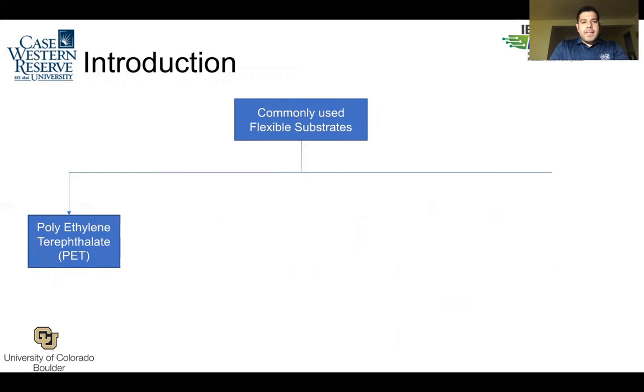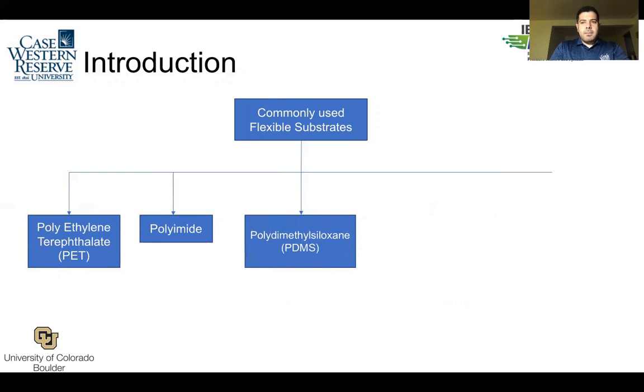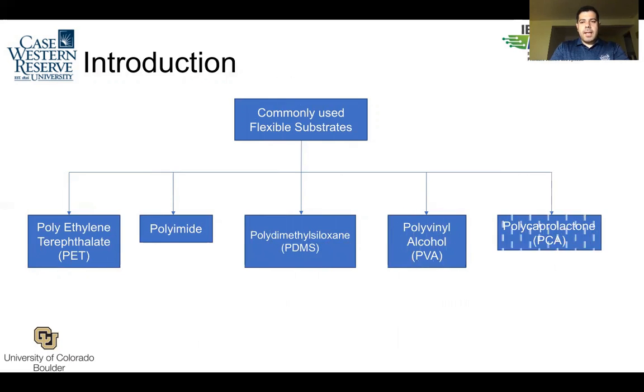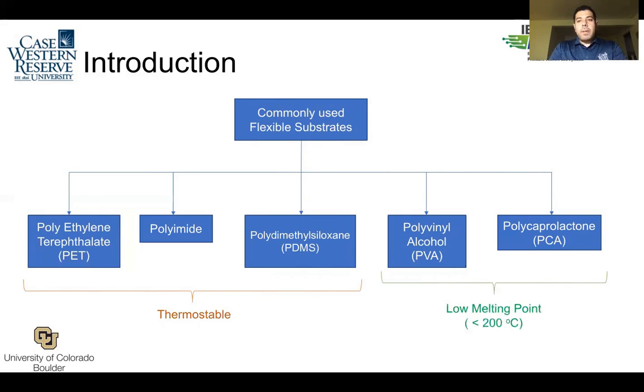We have PET, Polyimide, PDMS, PVA, and PCA. The first three are thermally stable. They can withstand high temperature, so there is no issue if you want to print a metallic ink on this substrate, and then you want to cure them at high temperature. But as for the PVA and PCA, they have a low melting point, below 200 degrees Celsius. So high temperature annealing will not work on these substrates if you are to sinter them.